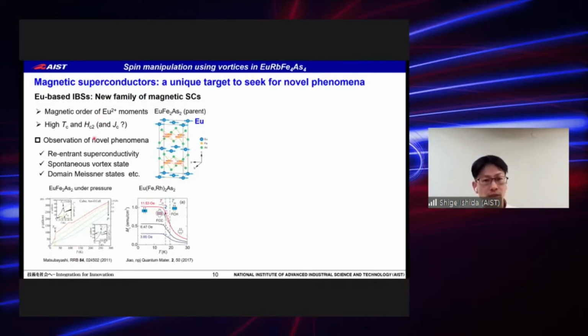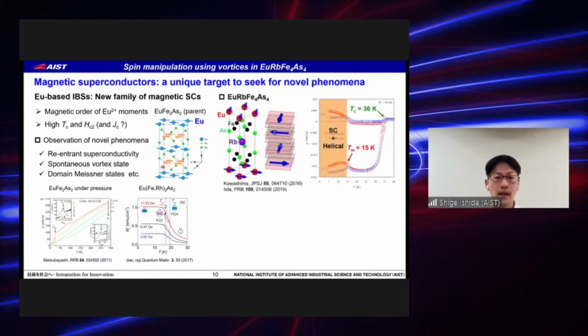In fact, there are various observations of novel phenomena such as reentrant superconductivity and spontaneous vortex state and so on in the europium-based iron-based superconductors. In this study, we focus on europium rubidium 1144, which showed the highest TC around 36K and high HC2 around 70 to 80 Tesla, the highest among the europium-based IBS.